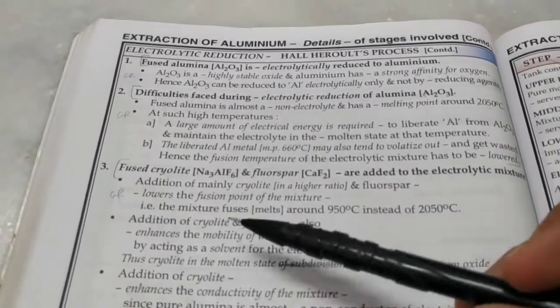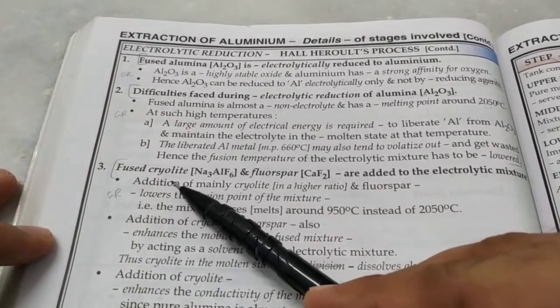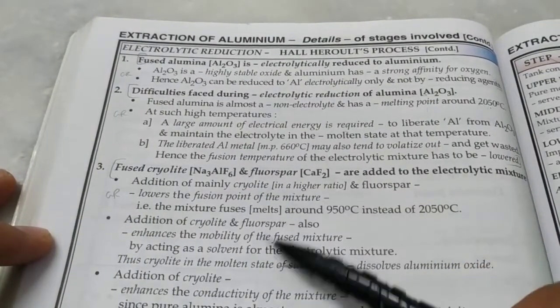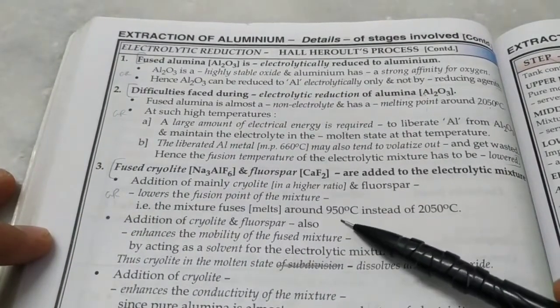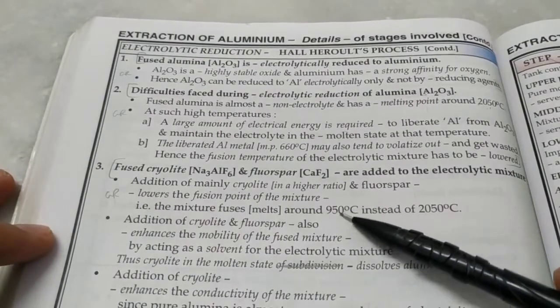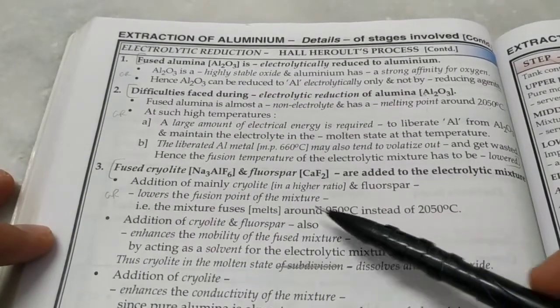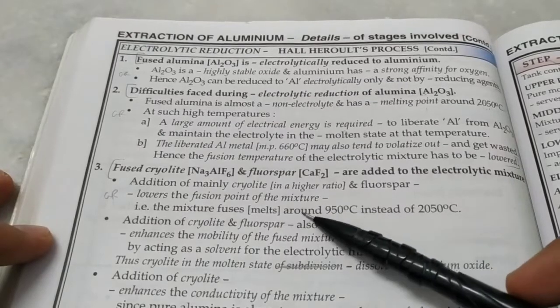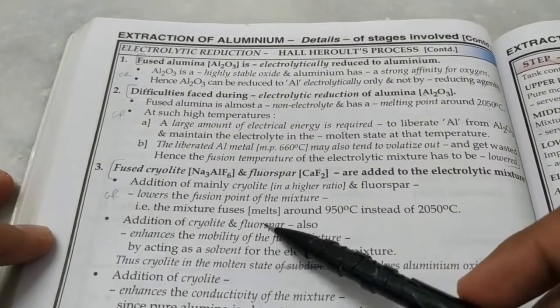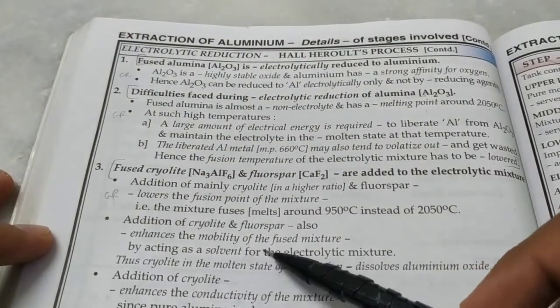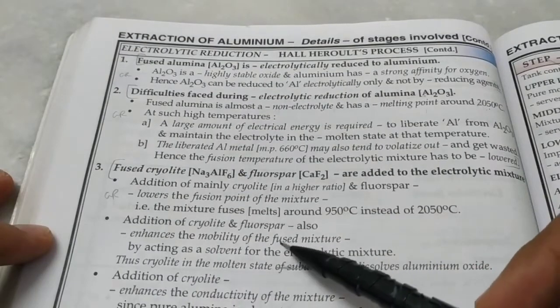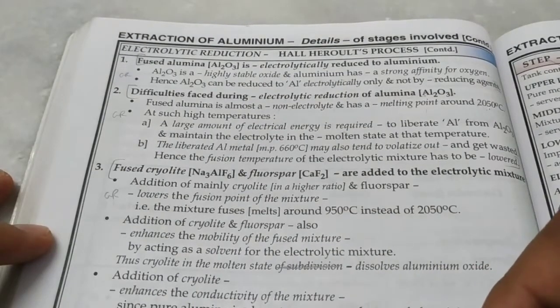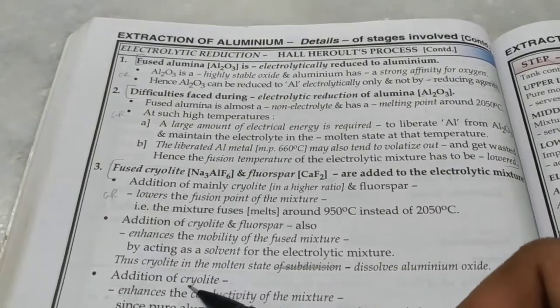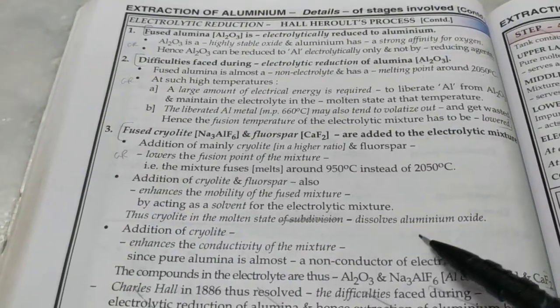And to the rescue comes fused cryolite and fluorspar, because when they are added, the melting point drops to just 950 degrees Celsius. So it's easier to maintain this temperature. Remember the ratios in which they are added. There is another advantage by adding cryolite and fluorspar. It enhances the mobility of the fused mixture. The ions move more freely in the electrolyte. And of course, the cryolite easily dissolves all the aluminium oxide in it.